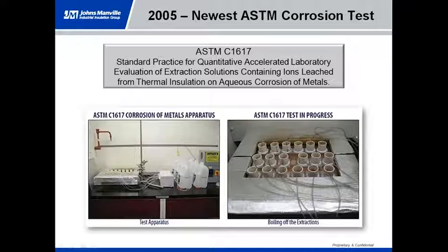Now, what's involved with this test is the insulation material is ground up with distilled water. You take a metal coupon and you weigh it, and then you glue a tube to it, which you see in the image on the right-hand side, and you drip this insulation solution on top of the plate that's heated to a temperature of 230 degrees plus or minus 10 degrees. The point is that as this water boils off the surface with this leachate, that creates a very corrosive environment. So that's what we're trying to simulate, but it's not to the point where you're dropping water on something that's really hot, or trying to boil the water off because it wasn't hot enough. It's just the right mixture of boiling to corrode that.